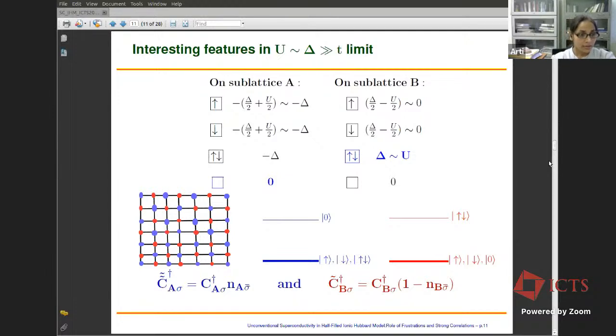As an effect, if you want to create an electron now in the low energy Hilbert space of the A sublattice, so suppose I want to create an electron with a spin up, I can do it provided there is a downspin electron at that site in the A sublattice, because there are no holes allowed in the low energy sector on the A sublattice. Similarly, on the B sublattice, I can create an electron with a spin up only if there is no downspin electron already present on that site in the B sublattice.